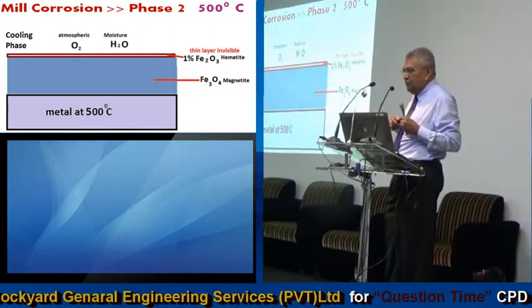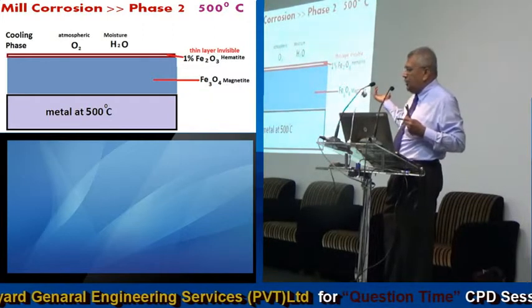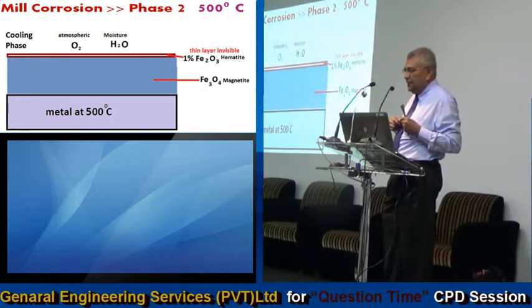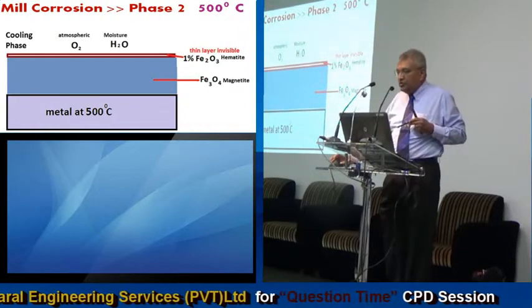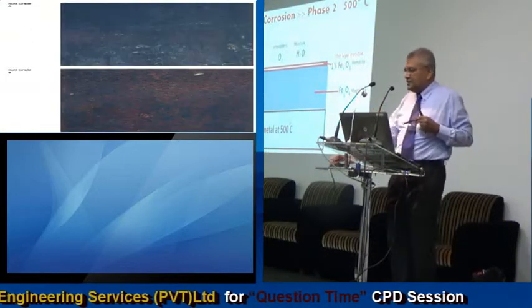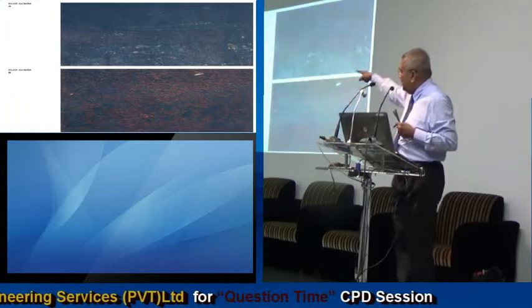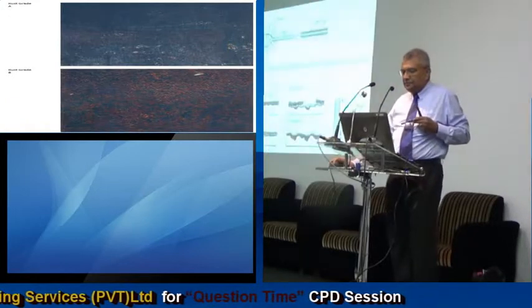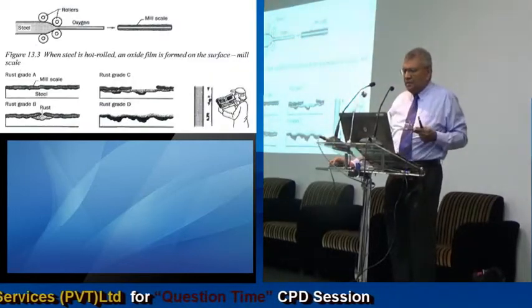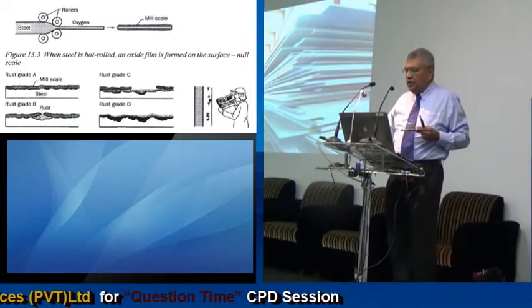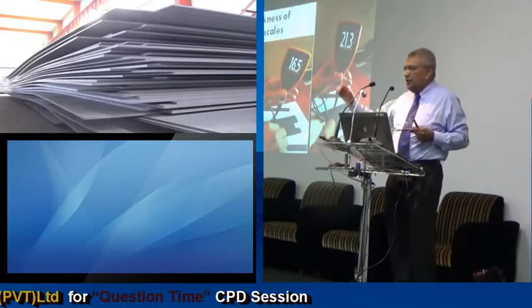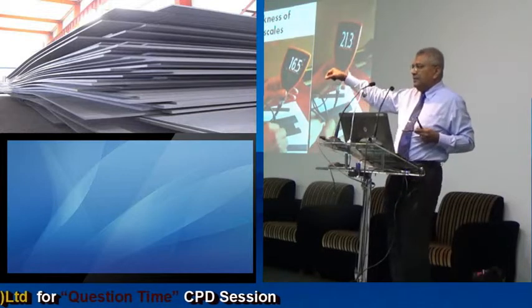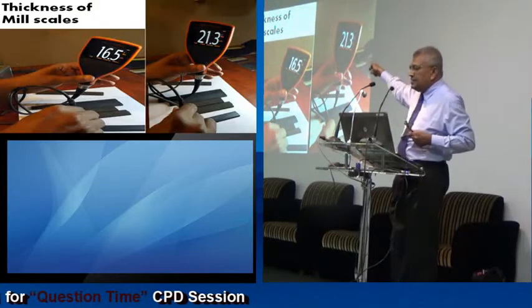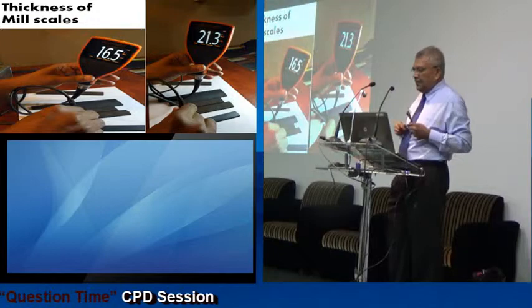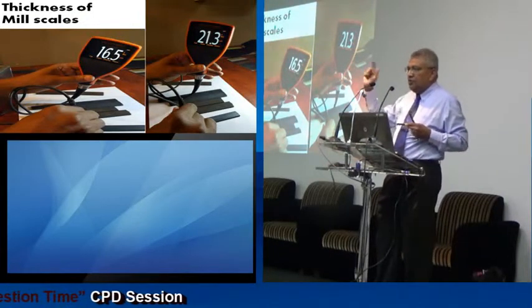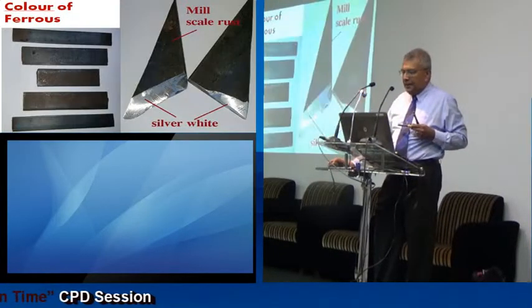For welding you have NVQs. But for corrosion there is no NVQ qualification, because I think nobody knows the seriousness of this. This blue scale, this is how the steel is manufactured, mill scale is happening. The new steel, 100% corroded. If I put my paint thickness gauge onto the mill scale, there are 16 microns of mill scale. We have to remove the 16 microns before applying paint.